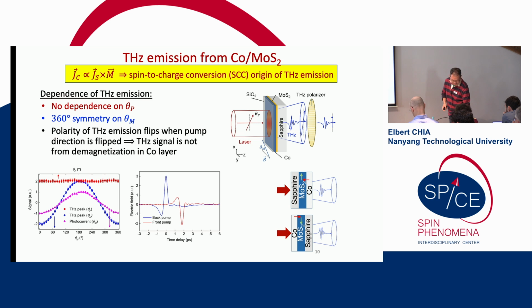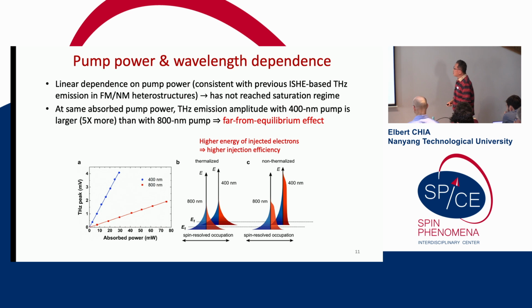And we then went on to do a pump power and wavelength dependence. So we pumped with 800 nanometers and 400 nanometers, and the x-axis is the absorbed power. If this process is a near to equilibrium process, then these two lines should actually overlap with each other. However, you can see that it is very, very different. And so we concluded that where we pump with 400 nanometers, there's a higher injection efficiency. So it has to somehow be related to the fact that these electrons that are pumped with 400 nanometers are very far away from equilibrium.